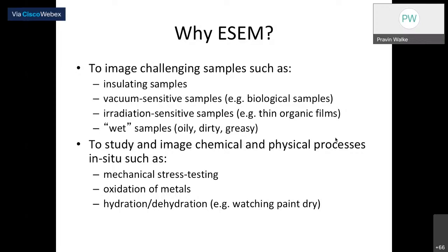So that deflection will not properly give you the required signals to the detector. Therefore, most of the time during specimen preparation, people talk about conducting coating on the insulating sample, so that you can see the morphology of that insulating sample. To avoid the charging effect, we need to have a conducting coating on the surface. So most of the insulating samples will get coated. Even semiconducting samples, to avoid the charging effect, need a thin conducting coating in order to ground the excess electrons generated on the surface.